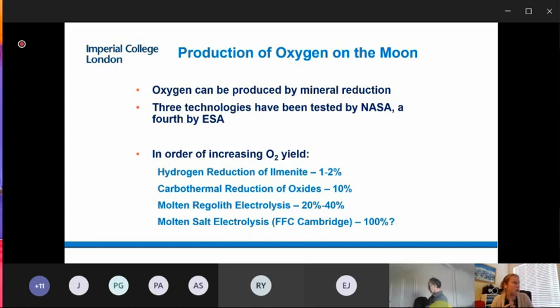So effectively what we want to do is heat up the regolith and release the oxygen. And that's exactly what the first two technologies do. We have hydrogen reduction, which is the lowest temperature. It operates around about 900 to 1,000 degrees C. We use hydrogen to reduce the ilmenite, but it will only give us around 1 to 2% oxygen yield. And we'll talk about that a little more in a second. We can use methane to reduce the oxide minerals, and that will give us a higher yield, but we need